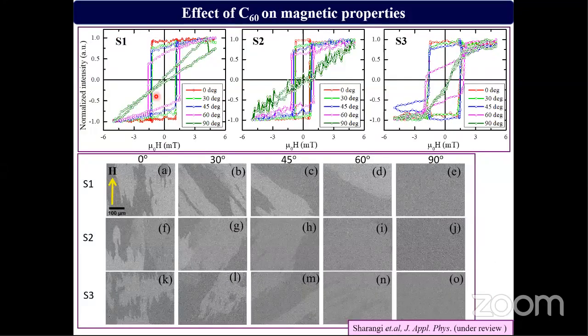So this is the hysteresis loop and corresponding domain images for all the 3 samples. The red curve is the hysteresis loop at 0 degree, and this green curve is the hysteresis loop at 90 degree. So we have seen that the hard axis is at 90 degree and the easy axis is at 0 degree, which tells that uniaxial anisotropy is present in this system. And for all the systems this is the same. So all the systems exhibit uniaxial anisotropy.